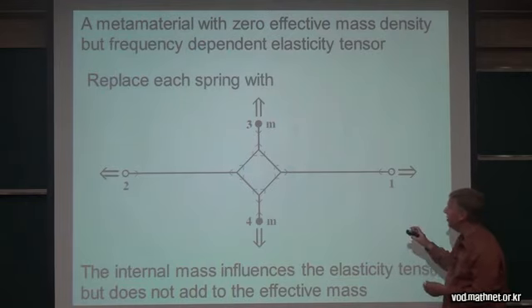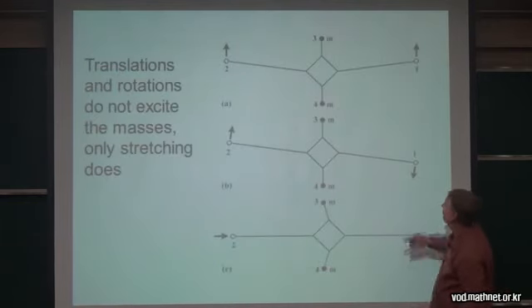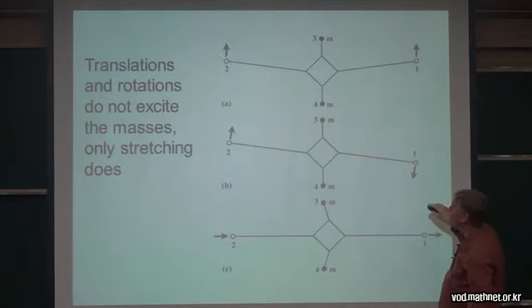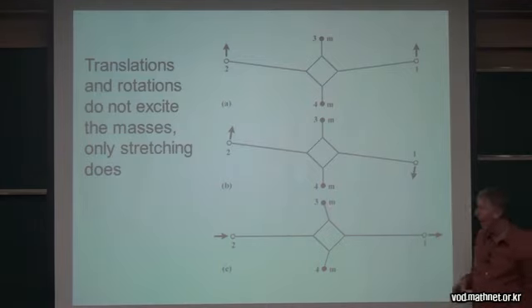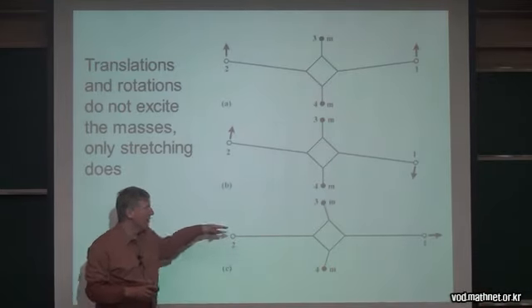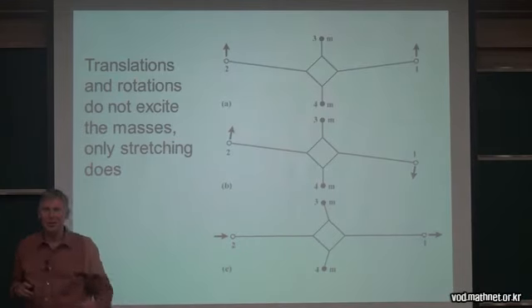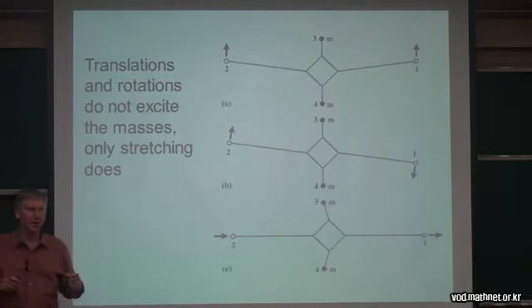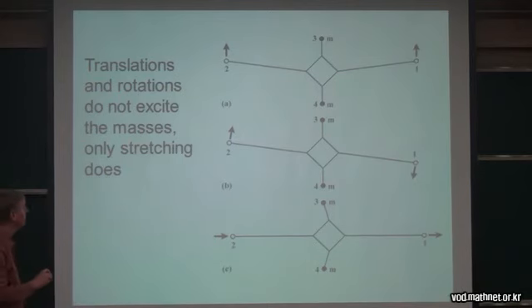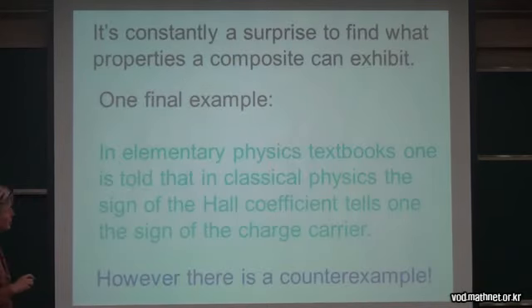because if I take this same geometry, I find out that I can, within linear elasticity, translate the ends in this direction or in this direction or in that direction, and the masses essentially don't move. And so small displacements of the terminals don't lead to any inertial force. So it's got a zero effective mass density, but nonetheless it's excited under stretching. Anyway, it's constantly a surprise to find what properties a composite can exhibit.